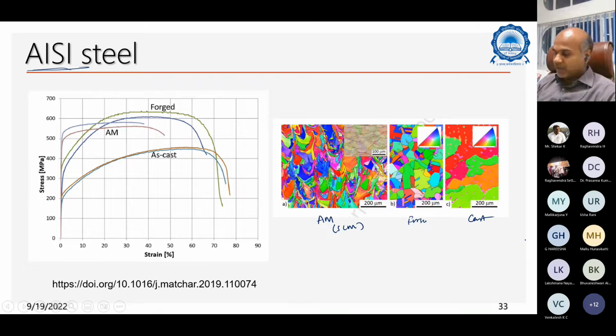If you look at the additively manufactured one, you see this kind of fish scale structure here, right? And which is pretty heterogeneous here, right? Some grains are bigger, some grains are smaller, and they are interpenetrated into each other. When you look at the wrought one, you see a very homogeneous microstructure here. Okay, in cast, you see a very big microstructure. Okay, look at the properties here. So cast material, because of the coarse grains, actually exhibits a good ductility, almost 60% you're talking about, but low strength.